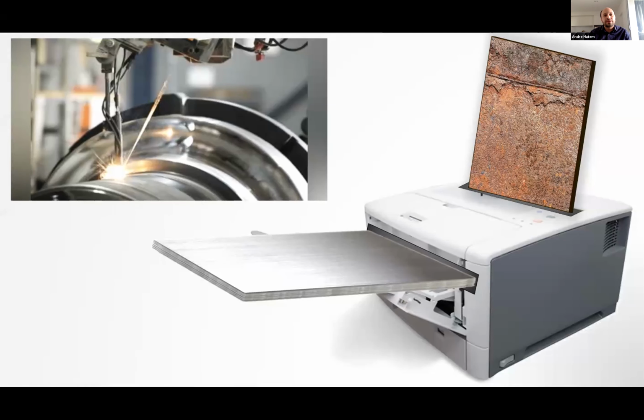Therefore, we conducted 2 different tests to assess the pitting response of these materials under a salt environment, following international standards. Our salt spray testing experiments up to 1,000 hours demonstrated equivalent or superior corrosion performance on the printed materials. Surprising, isn't it? But these were initial qualitative results. In a second experiment, we ran electrochemical corrosion tests that could actually identify and quantify the corrosion response of the materials. Here, all the three printed stainless steels present better resistance to corrosion than the conventionally produced alloys.